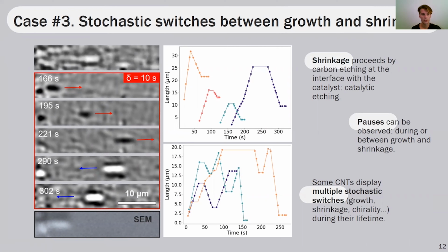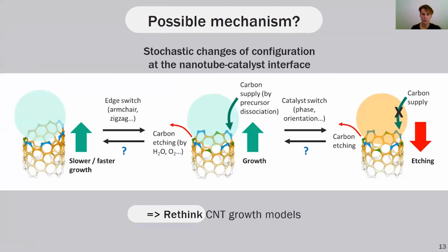And it's important to notice that shrinkage proceeds by carbon etching at the interface with the catalyst, that is, by catalytic etching. And also pauses can emerge between two steps of growth or between growth and etching, and even some nanotubes demonstrate multiple stochastic switches between growth, shrinkage, and regrowth. So now I would like to pass to a possible explanation of the mechanism of such behavior.